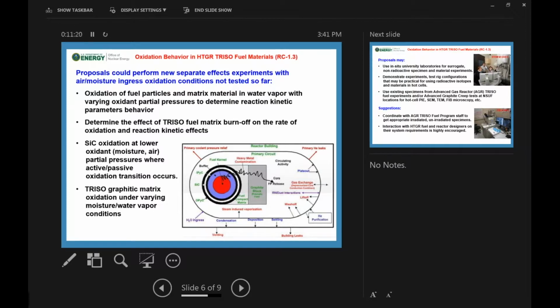So if you can do separate effects tests with air moisture ingress oxidation that have not been done so far, and for instance, oxidation of fuel particles and matrix materials in water vapor with different oxidant partial pressures, and if you could determine reaction kinetic parameters behaviors, that would be great. We would like you also possibly to look at the fuel matrix burn off rate in these conditions and the reaction kinetic effects. You know, the actual calculation of the rates versus temperature versus pressures would be very useful. Again, oxidation of the silicon carbide layer at lower oxidant air and moisture partial pressures in that transition regime, and then matrix oxidation under varying moisture and vapor conditions. So I wanted to give you some ideas of what you could propose.